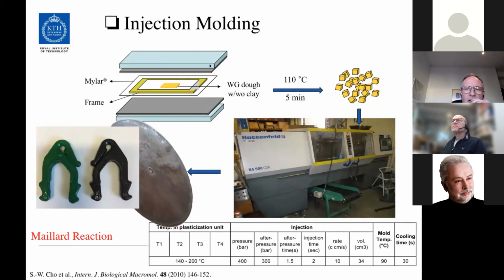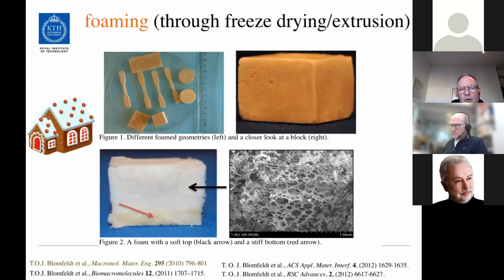You can injection mold the materials. That's, I would say, a bit easier than extrusion. Here are some examples to the left here, where we have a coated injection molded item, and then an uncoated one to the right, the black one. But it's readily injection moldable. You can also foam the materials. And in this case, you see examples of vacuum or freeze drying, I should say, which is not really an interesting process commercially, but it allows us to make foams readily and in different geometries. But we're also extruding foam. We also use foam extrusion.